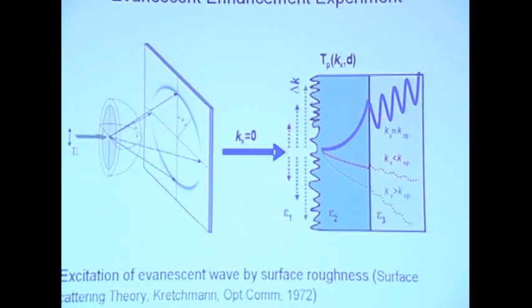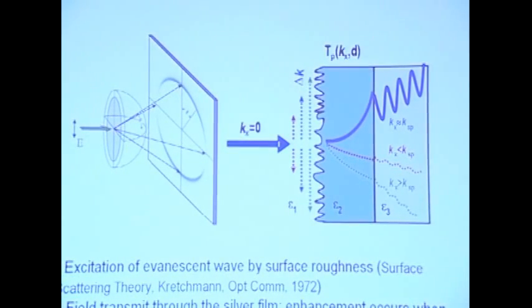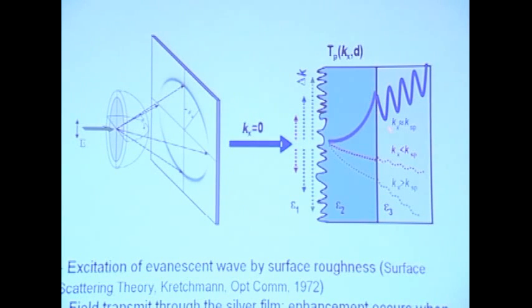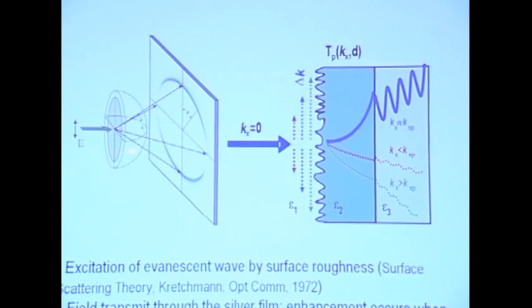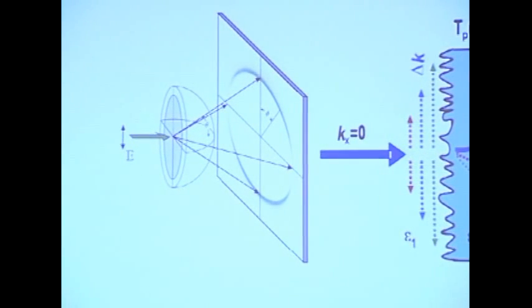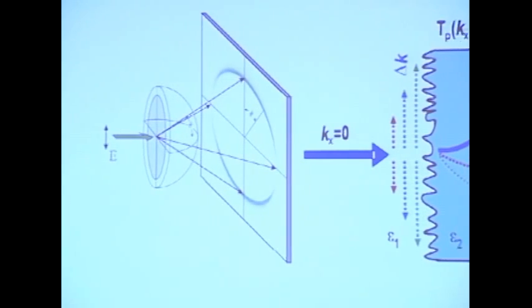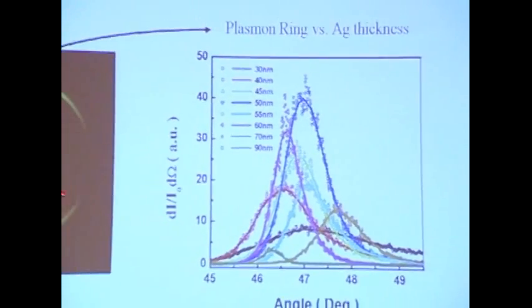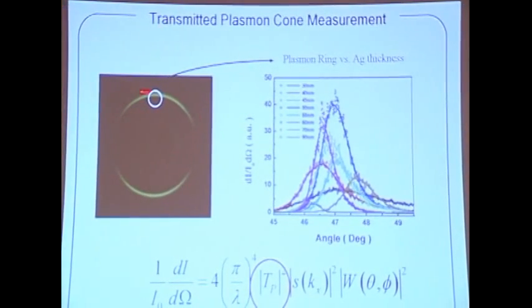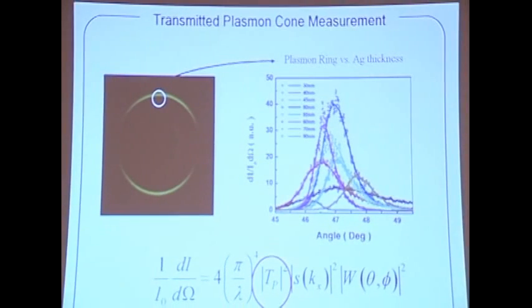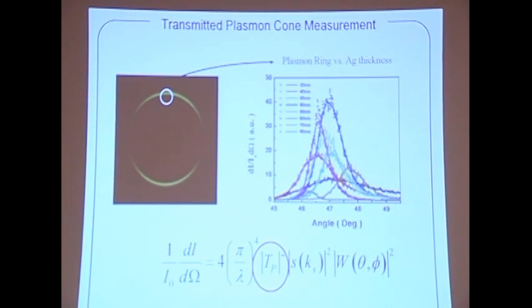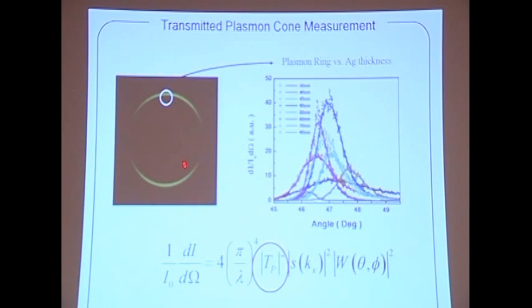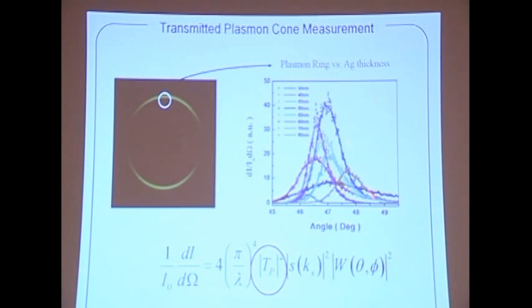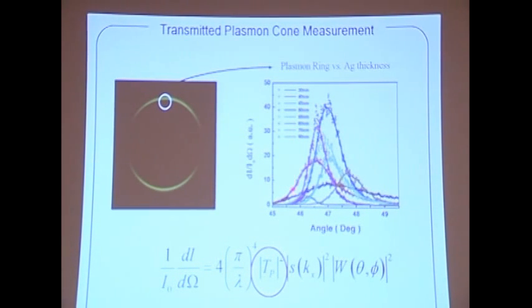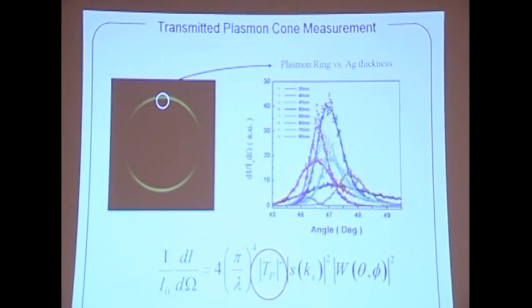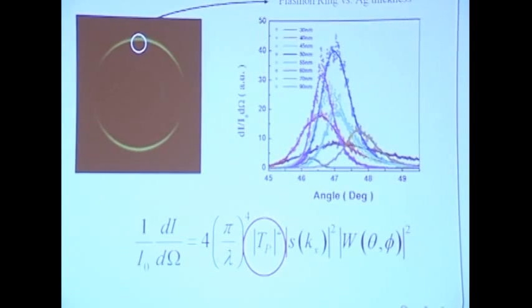However, even if this is enhanced, it is still an evanescent mode or surface mode. How are you going to detect it in the far field? In this case, we use a piece of hemispheric lens, and that couples this special k into a propagating wave that you can measure in the far field. And this is a far field measurement where, because this is polarized light, it's not symmetrical. So what we see is a plasmonic cone coming out. And this cone gives you a lot of rich information by plotting this over the angle direction. So this is the angle direction, and with different metal thicknesses, you can plot this angular distribution that essentially gives you the solid angle information of the scattering.